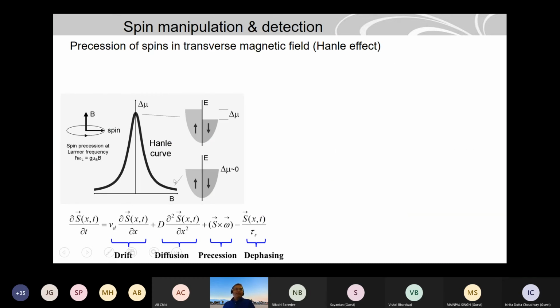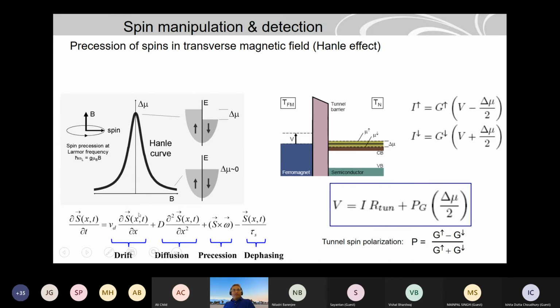So how to detect it? You can again use the Hanle spin precession measurement. You apply a perpendicular magnetic field, so the spin splitting delta mu you create in the silicon by spin injection should go to zero. They will be equal at this stage, so your voltage signal should behave in a similar way. You can also solve this equation, but you can remove the drift term, because if you don't apply the electric field, it should not be present. You can also solve the equation for the conductance, how the spin up and spin down conductance and the spin accumulation behave in the semiconductor. The voltage signal you see here is directly proportional to the spin accumulation you created.